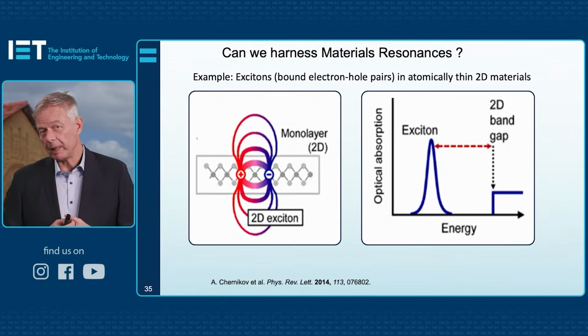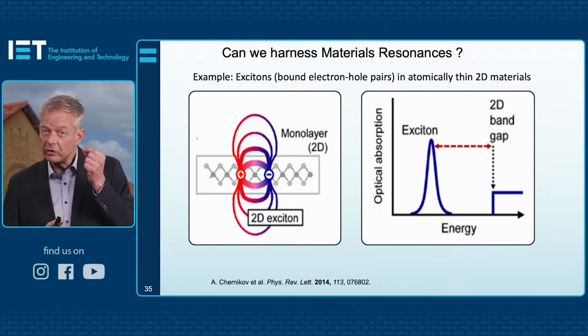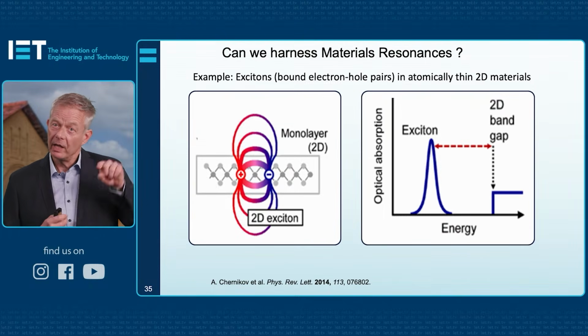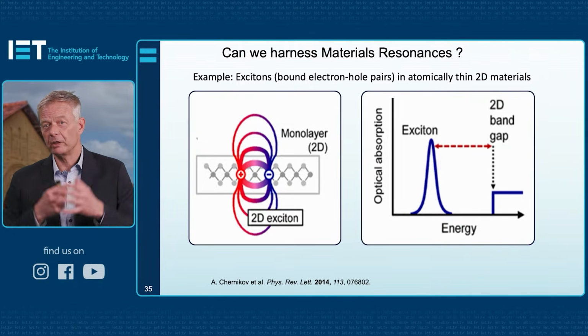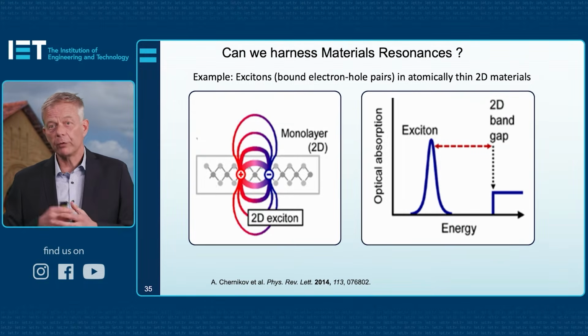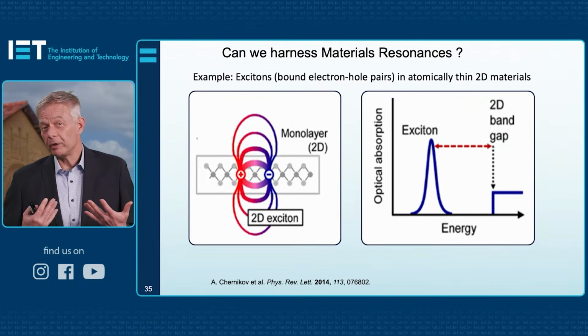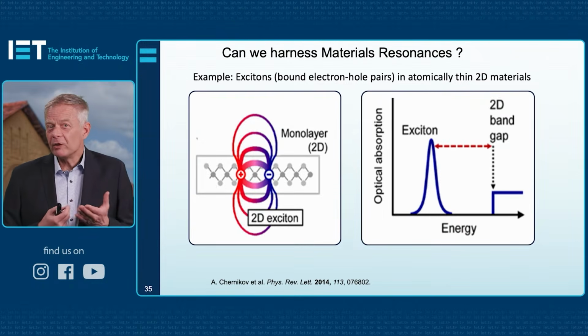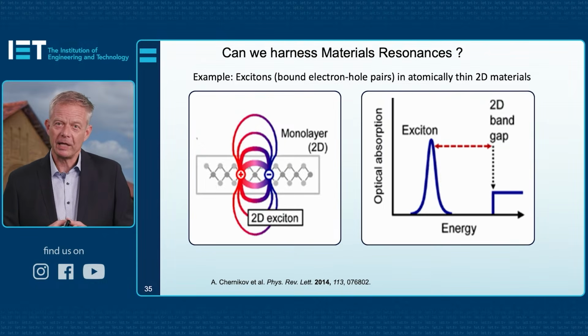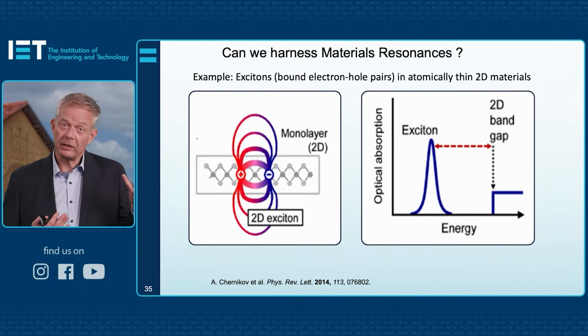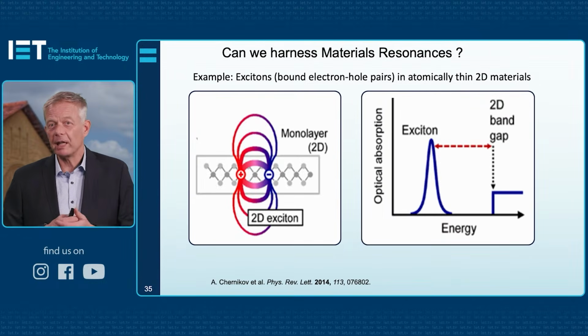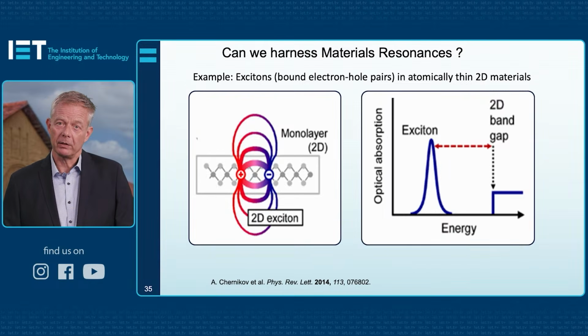If you look at the absorption spectrum of such a thin film, then you can see the ability to excite excitons as a very sharp resonant feature called the exciton peak, typically far away from the absorption across the band gap of the semiconductor. Now, as an optics person, I was looking at images like this, absorption spectra, thinking this is a beautiful resonance. Can we harness them like the plasmon resonances in metal and whispering gallery mode or Mie-type resonances in semiconductors? Can we use them in the same way? If so, we may be able to make atomically thin optics that can switch and redirect beams extremely fast.